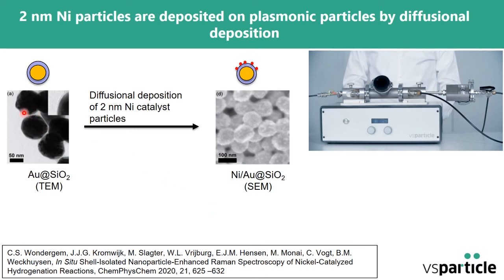These are the plasmonic particles. They are covered by a layer of silica, and in this case 2 nanometer nickel particles have been brought to the surface by diffusion using this small diffusion sampler here. Okay, this is the last application I wanted to mention.